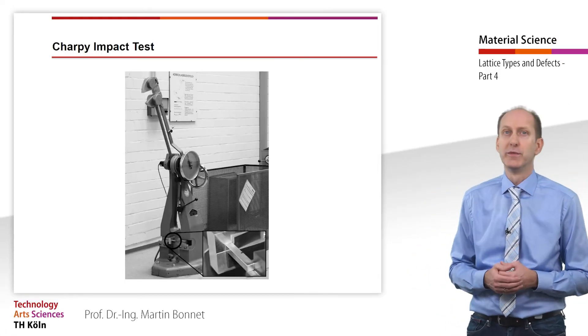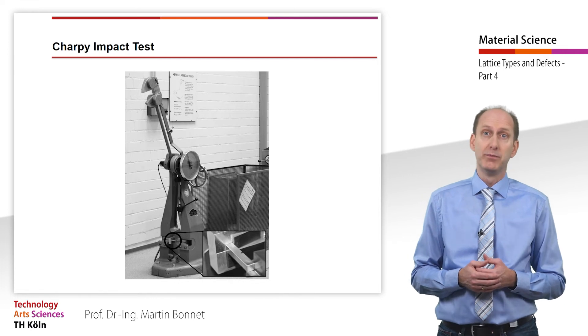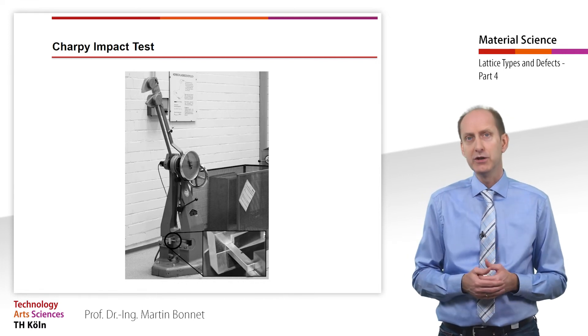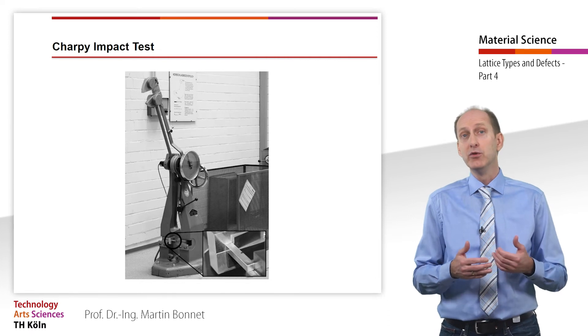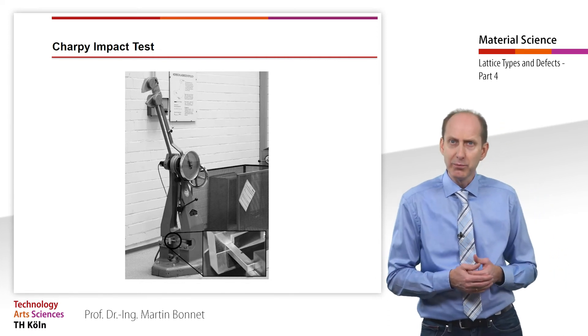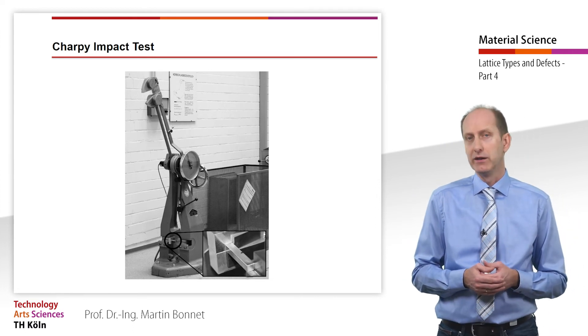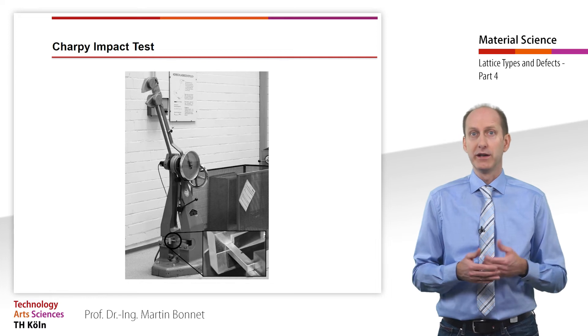Since the toughness of a material also depends on the temperature, specimens are brought to a desired temperature in a climatic cabinet and then removed immediately before the test. The specimen is then placed with a notch in the direction of impact in the pendulum impact tester and the pendulum is released.